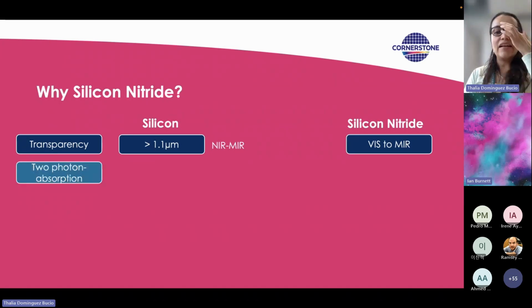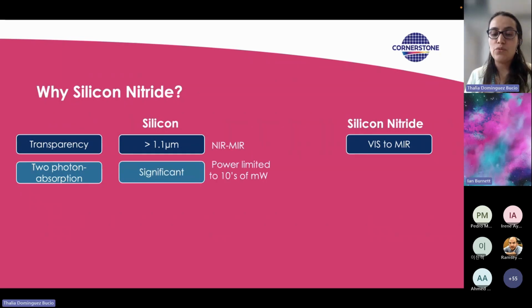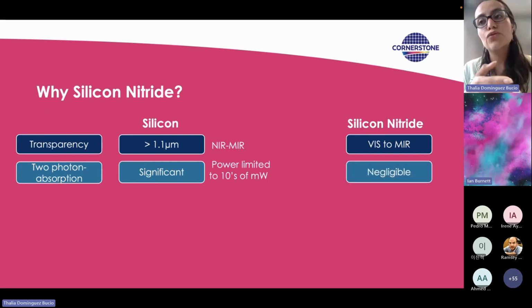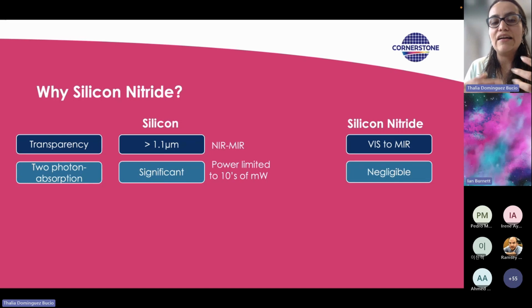Then again, both silicon nitride and silicon possess nonlinear properties. They can be used for nonlinear applications because they have a nonlinear coefficient, in this case, chi3. The main difference between these two materials is that silicon possesses a significant two-photon absorption, which means that if you're doing a nonlinear process, or even normal processing, in which you're pumping a lot of power in your circuit, the power that you can handle in your waveguides is limited to only tens of milliwatts. Now, if we look into silicon nitride, this is not the case because the two-photon absorption is negligible. So even though the nonlinear coefficient is a bit lower, we might be able to get a nonlinear process that is good enough for the application that we need because it's not so affected by the nonlinear absorption losses.